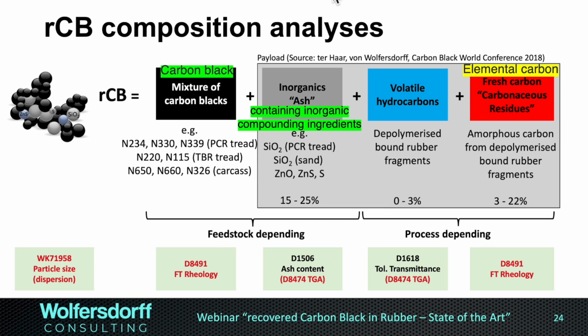Volatiles are a little bit easier to determine. If it is for the PAH, the polycyclic aromatic hydrocarbon content, we have the toluene transmittance, D1618. We have the new thermogravimetrical analysis, the D8474, which is also great to tell us more about the ash content as well, or the inorganic content. Again, the type of mixture of carbon blacks we can determine also with the Fourier transformation rheology.